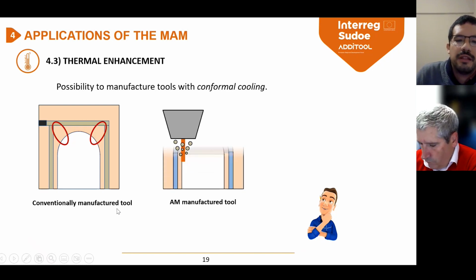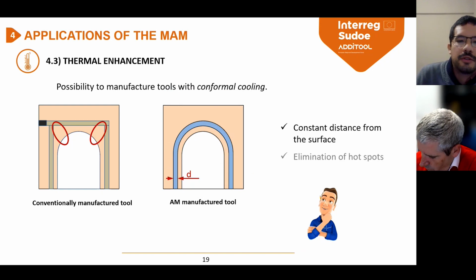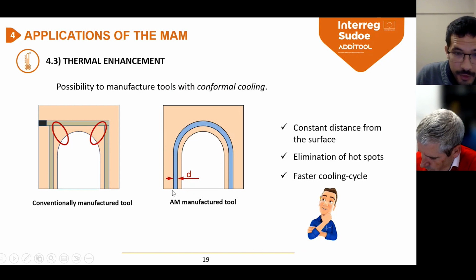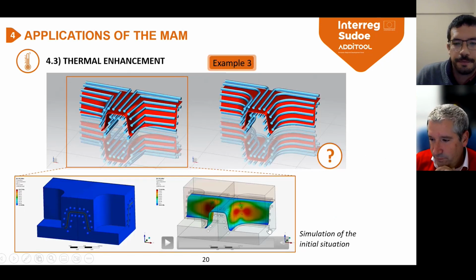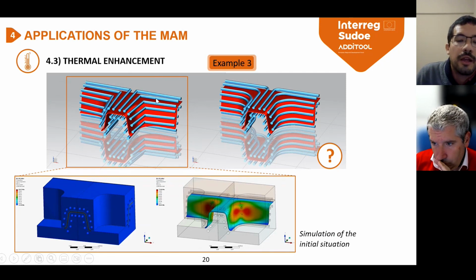So in this case, thanks to the additive manufacturing process, we can manufacture a cooling channel which is always at a constant distance from the surface. We eliminate the hot spots we have talked about before, and also we can obtain a faster cooling cycle. In order to show this feature, I'm going to share with you the results of thermal simulations which we ran with the software ANSYS.